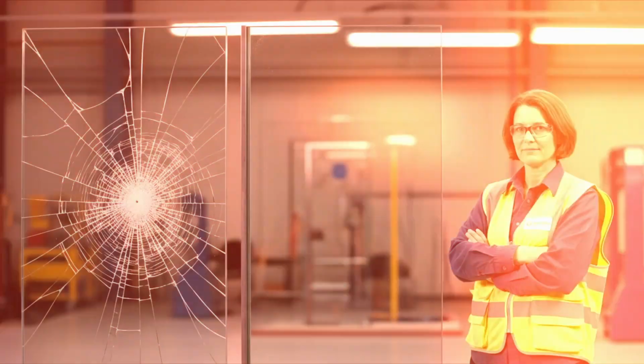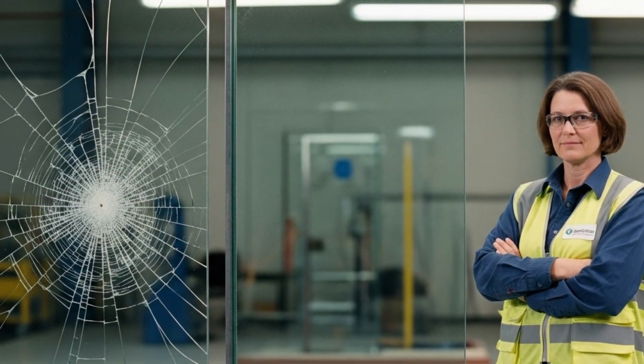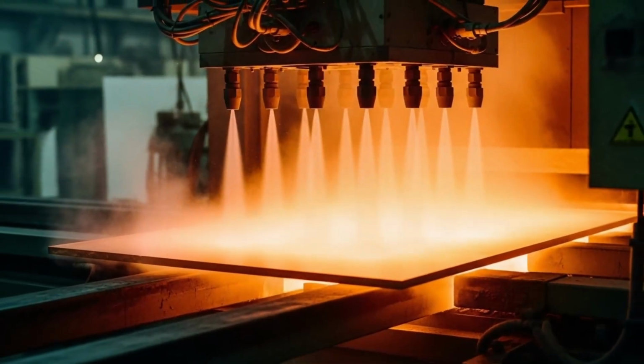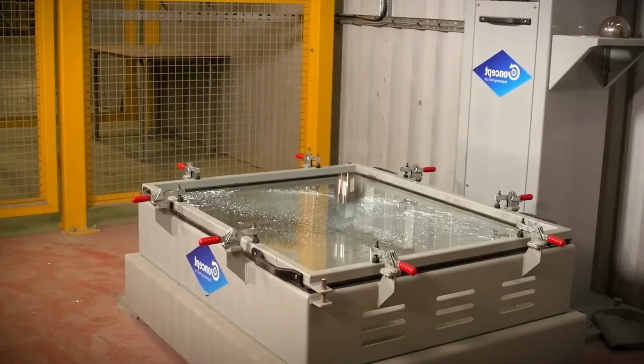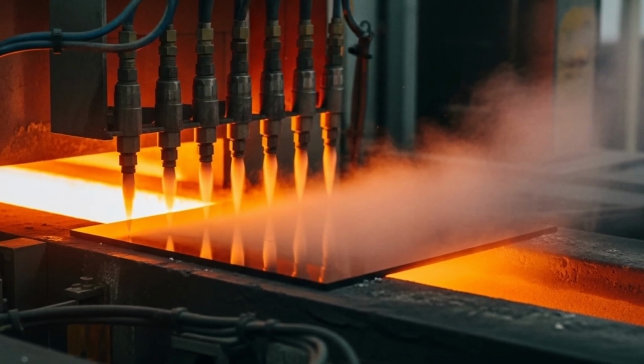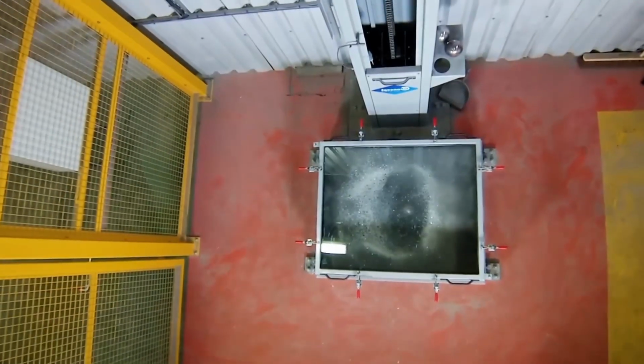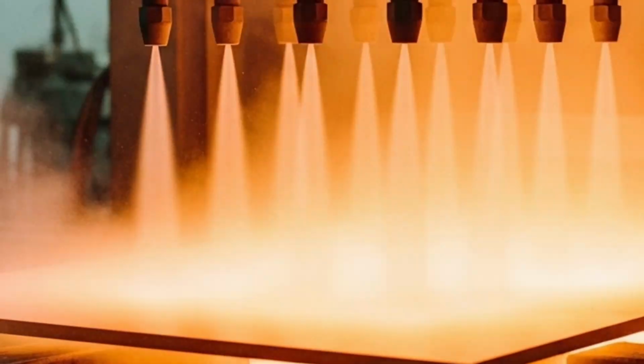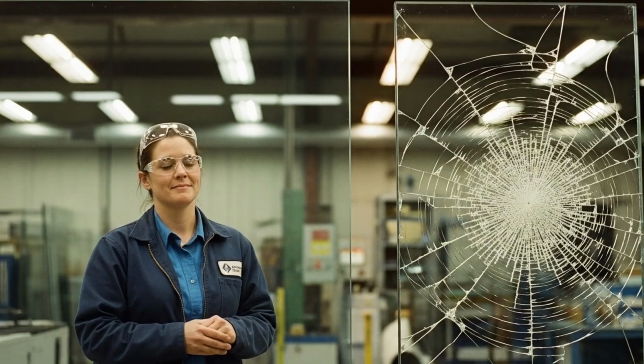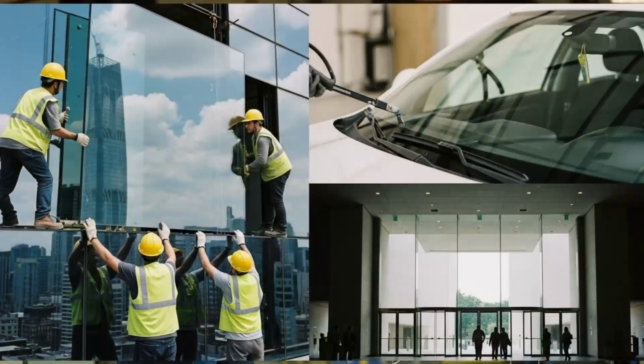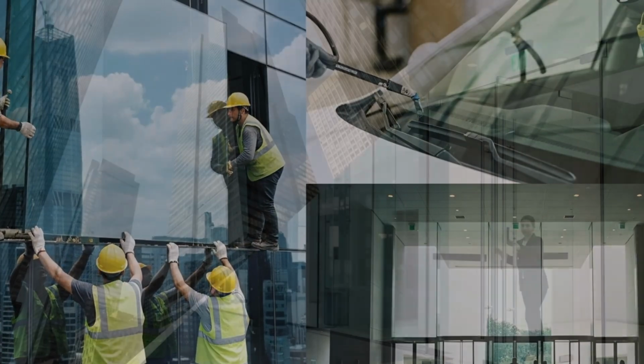Next come the quality tests. Entire panels are subjected to impacts with steel balls or to pressures simulating extreme winds and accidental blows. In the case of tempered glass, the goal is that, if it breaks, it shatters into tiny fragments, like a spider web, reducing the risk of serious cuts. This effect is achieved during tempering, where panels are heated to about 620 degrees Celsius and then cooled rapidly with high-pressure air. The result? Glass up to 5 times stronger, essential for cars, facades, and skyscrapers.